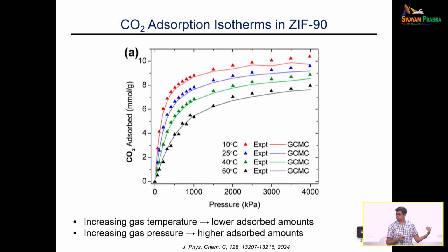Adsorption, like I said to start with, is expected to be an exothermic process. If you have higher temperatures, adsorption is going to be very severely impacted. So if you look at the first, this is 10 degrees, this is cold for a process. You can do it in the lab, but replicating 10 degrees in an environment, yes, you need cooling to get there, versus 60 degrees, which is probably the temperature for most flue gases, even after a certain length of the stack. You see the difference in capacity, that is quite a lot. So temperature has a very big impact.